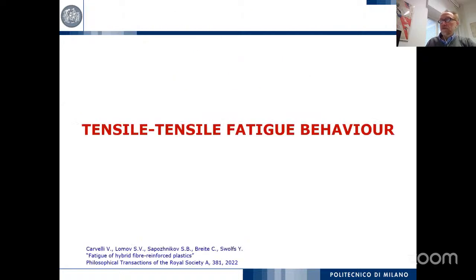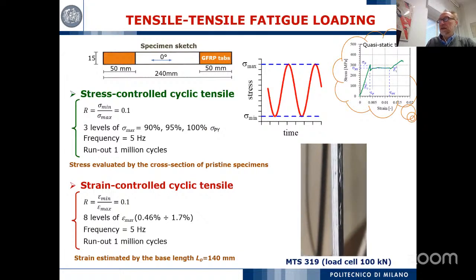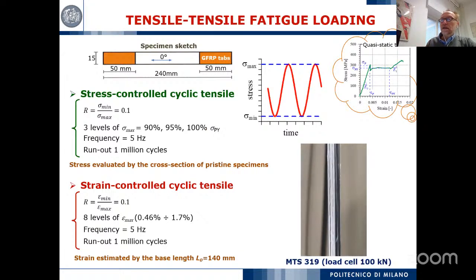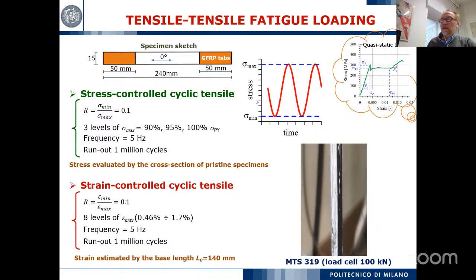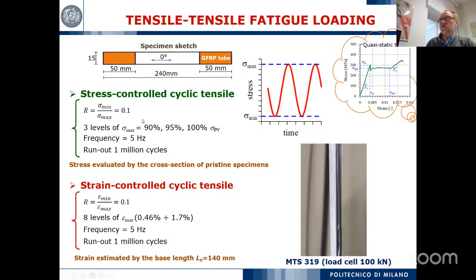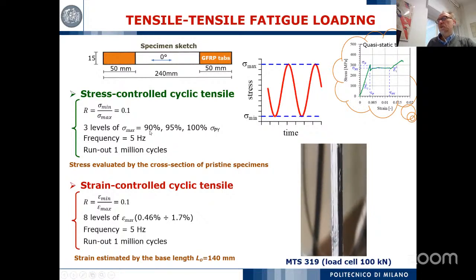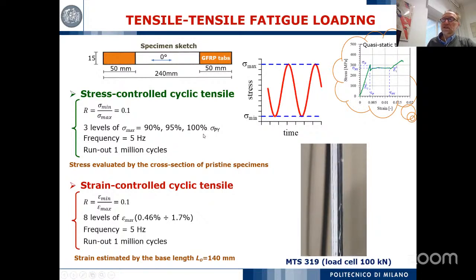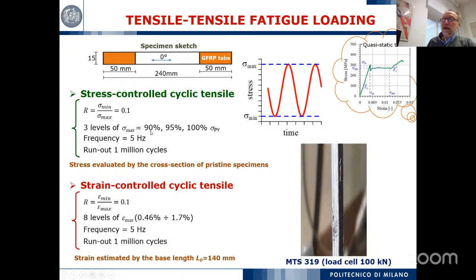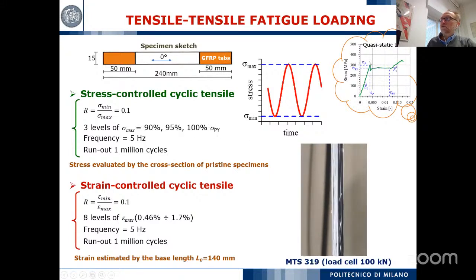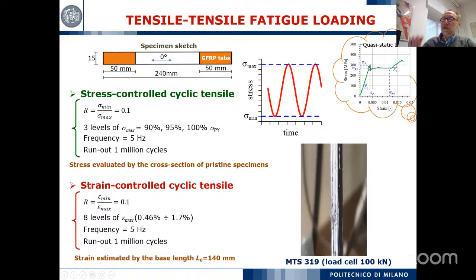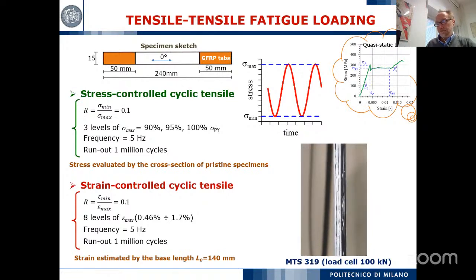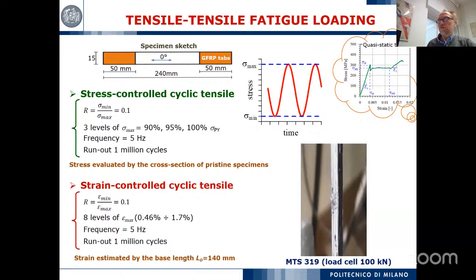Moving to the behavior in terms of fatigue, we limit our test to the tensile loading, and we limit this test to quasi-isotropic laminate, changing the control of the test. We have some tests with stress control with this 0.1 ratio at 3 different stress levels that are from 90 to 100% of the stress at the first peak, so at the very beginning of the plateau.